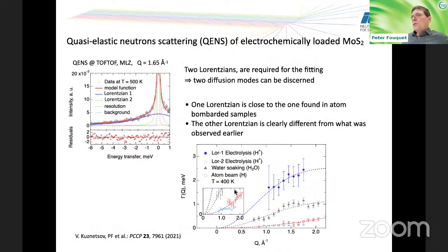And what we also saw when we looked at the data with quasi-elastic neutron scattering, and these measurements were done in Munich at MLZ, is that we saw actually two different lines in the quasi-elastic signal, which means that we saw at the same time different processes of diffusion. And one of the processes is quite close to the speed with which we saw the diffusion in the atomic beam bombarded sample. We believe that we see really H2 motion, and we see hydrogen atom or hydrogen ion motion as well at the same time.